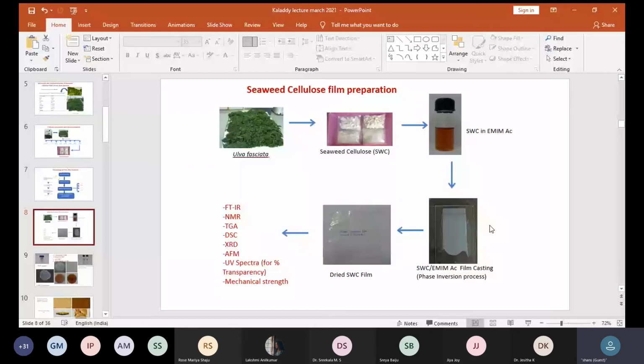Once we make the solution, we leave the solution at room temperature, or sometimes we do degassing, because even small micro bubbles may spoil the final polymer film. So we make sure there are no air bubbles inside the solution. Once there is no air bubble, sometimes we allow it overnight, like 12 hours, in ambient condition. We do the casting on the glass plate, and after casting, we put it in a coagulant solution. Generally, the solution is water plus some surfactant. Generally, we use SDS in a very minimum quantity, like 0.5 to 1%. When you soak it in the water for a few hours, we keep on changing the water and make sure the unreacted ionic liquid, whatever solvents we use, leaches out into the water. And we remove and dry it again.